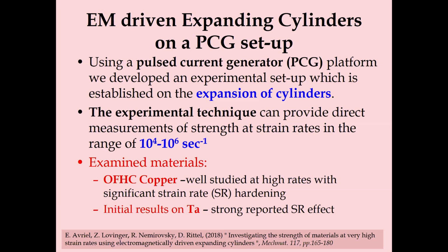And as we just started to establish this technique, we did a broad characterization on copper, which is a well-studied material and has a significant strain hardening effect. So we wanted to use that to see how this is working and compare with the data in the literature. And just recently, we started to get new results on tantalum, which is also reported with a very strong strain rate effect. So we have this here on the bottom. You could see a paper we had out 2 years ago on this developed setup.